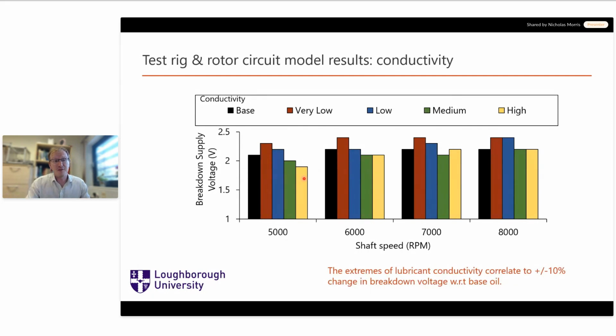Now, if you run these different conductivities, which vary from the highest conductivity of 1 times 10 to the minus 10 Siemens per centimeter to 1 times 10 to the minus 14 Siemens per centimeter, they're all very low conductivity fluids. For context, tap water will be about 1 times 10 to the minus 4. So we're getting on for 6 orders of magnitude less than the conductivity of water at best. So when you run these conductivities through the electrical model that I showed previously, you see almost no difference in terms of the voltage across the contact.